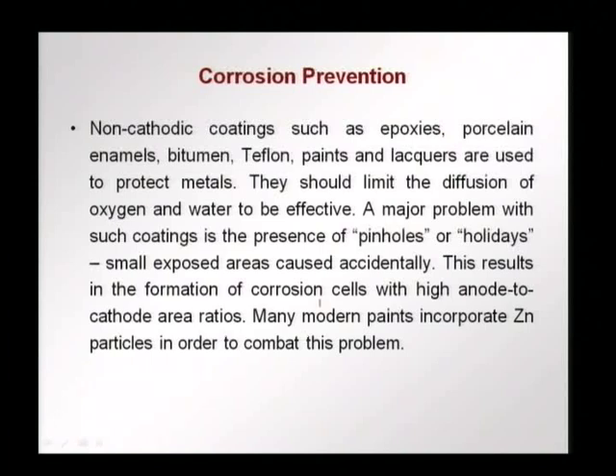However, a major problem is what are called pinholes or holidays. Holidays mean that there is a discontinuity in the layer. Small areas of the coating could be accidentally exposed due to a scratch or somebody cutting something accidentally, resulting in exposure of the base metal. This results in the formation of a corrosion cell with a high anode to cathode area ratio. There is a large area that is not exposed to oxygen, which can become anode, and a small exposed area which can become a cathode. So, there is a high anode to cathode ratio and there you could have a corrosion cell forming.